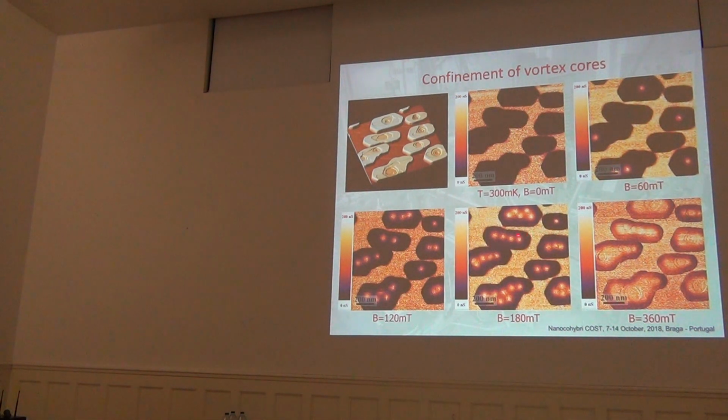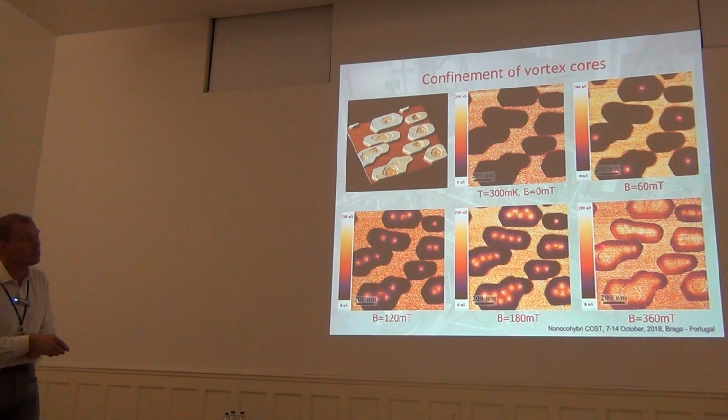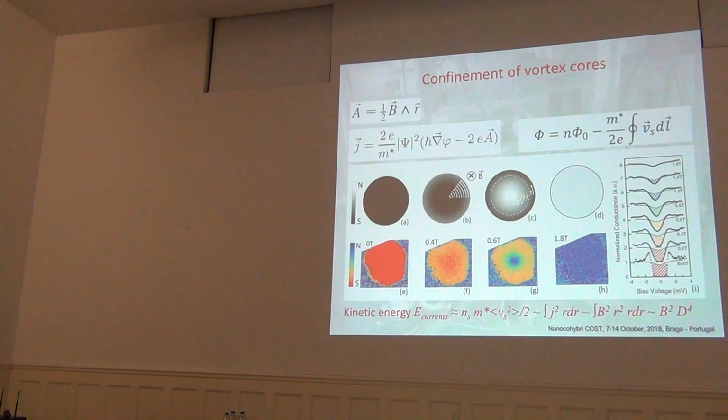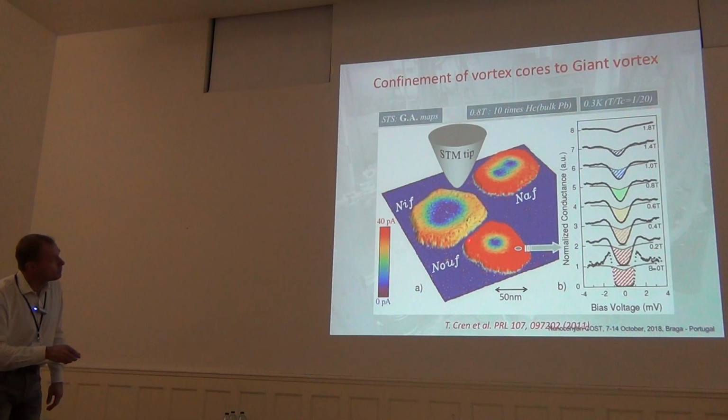In this region, the superconductivity survives. You see, the gap exists here, and even here, at higher field, where we completely suppress the superconductivity inside the island, the color is the same outside and inside. You still have the superconductivity in the border where the currents perfectly compensate each other. And this regime is called the HC3 regime. So HC2 is when the distance between Abrikosov vortices becomes comparable to Xi. But you can go further, you can still have surface superconductivity, and this is clearly the case. It's called the HC3 case.